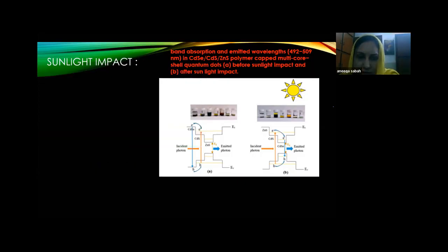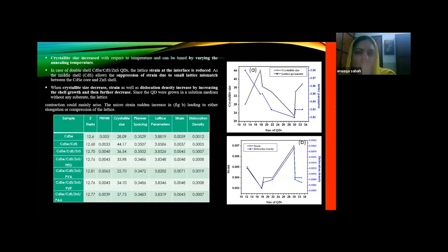If we go back to examine such, we also have mean crystallite size, dislocation density, strain, lattice parameter, full width at half maximum, and we find that in case of the double shell, the lattice strain at the interface is reduced, as the middle shell allows the suppression of strain due to small lattice mismatch between the cadmium selenide core and zinc sulfide shell.